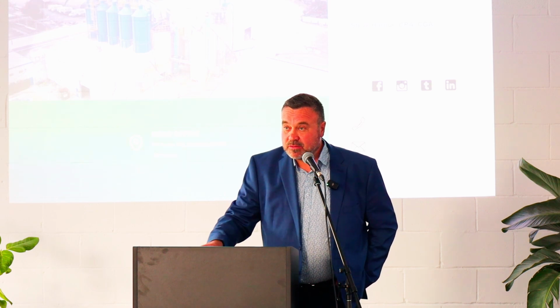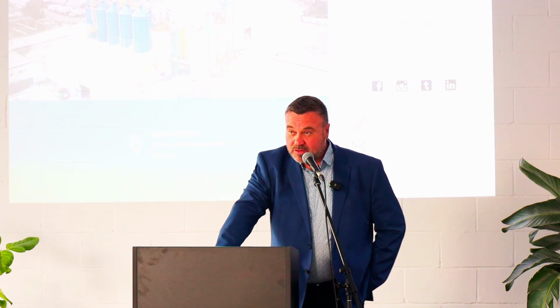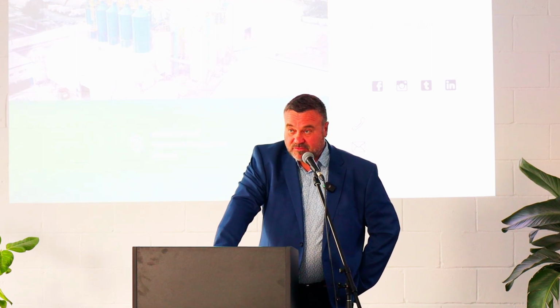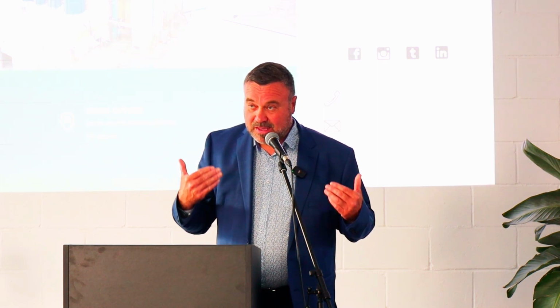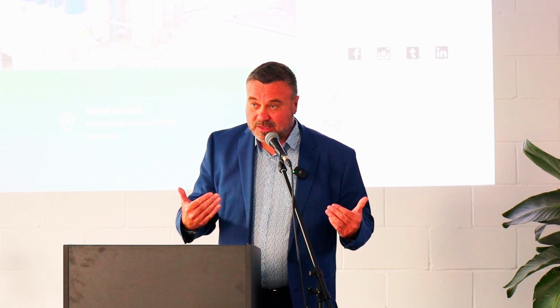Pyrogenesis has world-class patented technology in the efficient use of plasma for the transfer of heat. And we are seeking to see if we can economically transfer heat from a plasma to melt and then subsequently cool crystalline silica or quartz and make it into glass. Essentially, post-consumer glass is made for you to drink, and there's a whole bunch of things in it that are not great for cement. When we make a glass for cement, we are making it tailor-made, and it only has silica in it. And the higher your silica content, the stronger your cement.